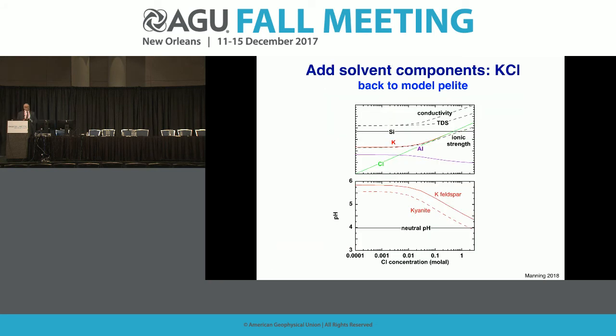If we go back to our simple calculations, we can, at least at low salt concentrations, think about what happens as we add chlorine to these solutions, and let it react with our model assemblage. You can see that as you add more and more chlorine on the x-axis, the concentrations of aluminum go up, and the concentration, obviously, of chlorine will go up, and potassium goes up as well. Silica stays the same. We're not detecting the decline in solubility over these low concentration ranges here.